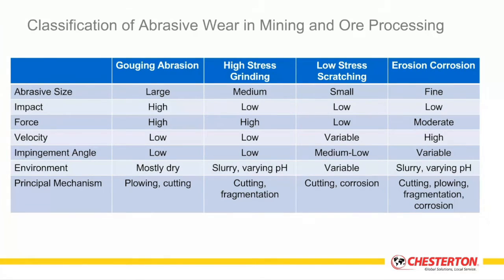Now, when we want to classify the rate and the degree of severity and how each one of these characteristics has an impact on it, I want you to look at this table here. What this shows you is, on the left, in the vertical column, the size of the abrasive particle, the impact force that's resulting, the total true stress force that's resulting, the velocity of flow, the impingement angle of the flow onto the surface, any other environmental factors that come into play, whether it's dry or wet, or if it's a high pH or low pH, and the principal mechanism of damage occurring. So you can see for something like gouging abrasion, the primary mechanism is plowing or cutting wear.